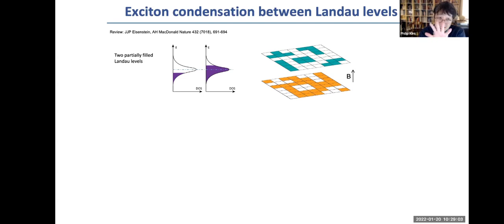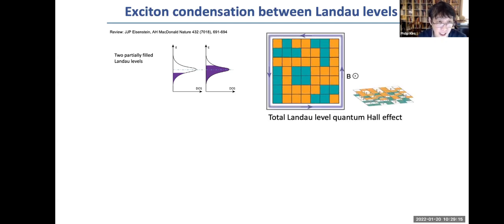In other words, if you add the densities of each together, you basically have a filled Landau level, which means that if you somehow take the Landau levels in the two different layers and make a projection, they can form one full Landau level as a single layer. So imagine that you have a very small separation between the layers, the top partially filled layer and the bottom partially filled layer. There develops a correlation between them, such that there is an organization of electrons and holes in both layers: when there is an electron in the top layer, electrons avoid the bottom layer, creating a hole in the bottom layer, and they can just kind of bind together almost, forming exciton-like states.